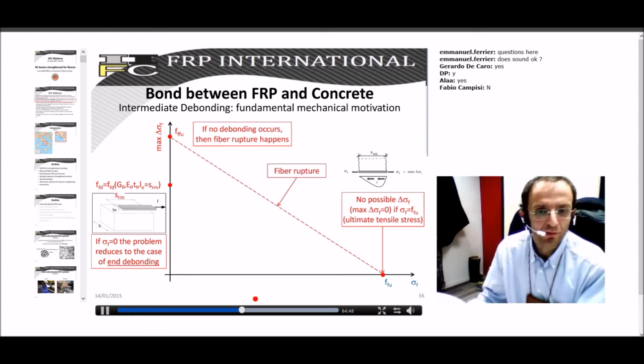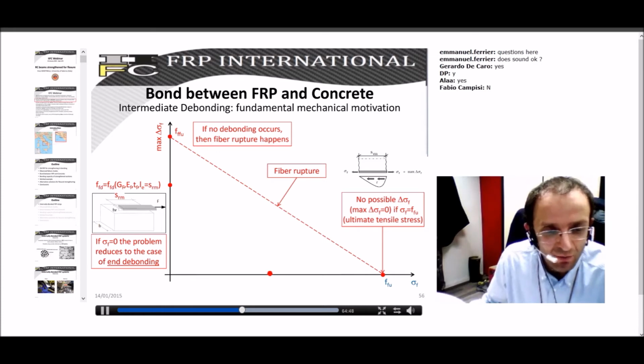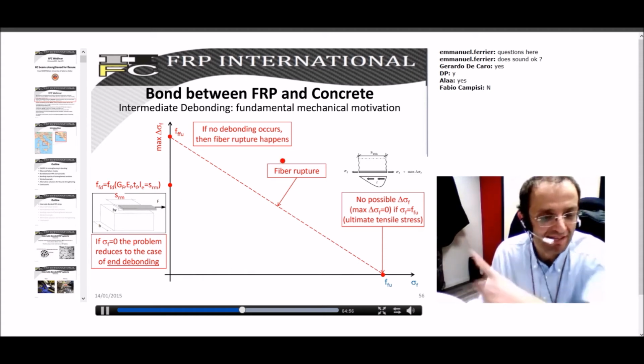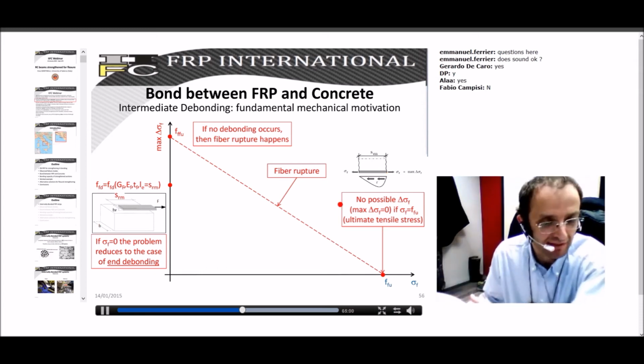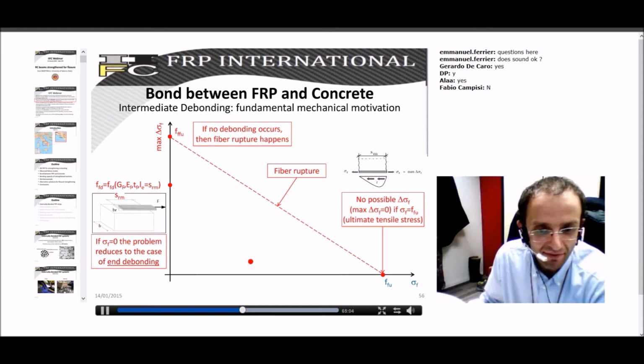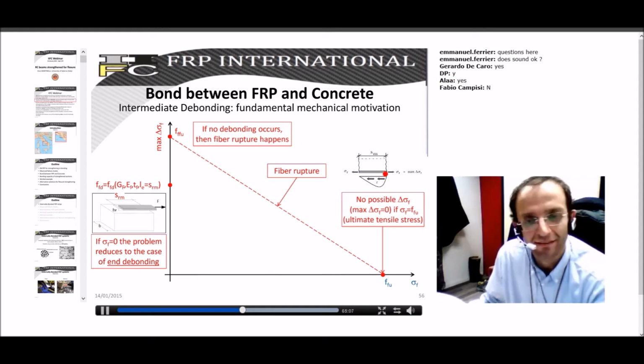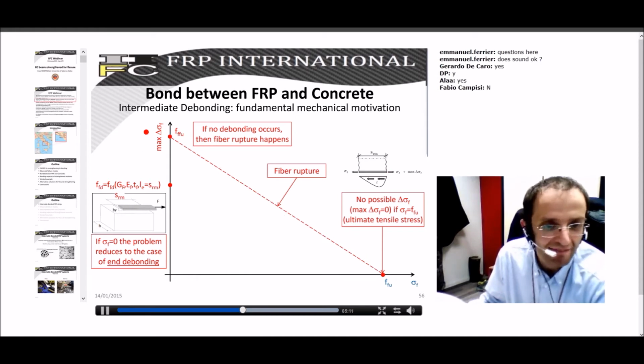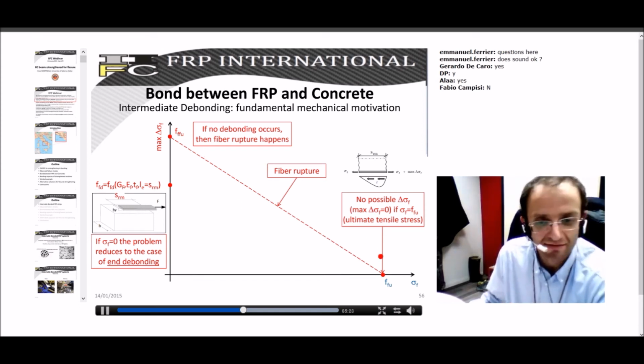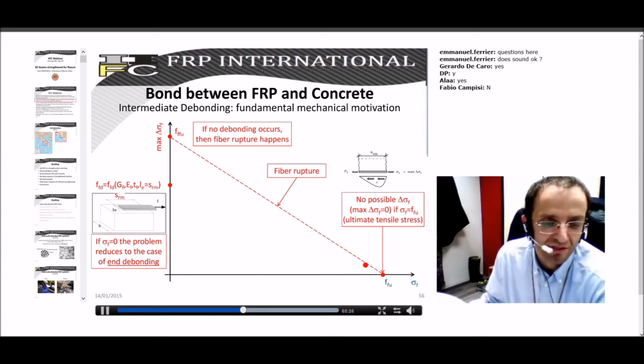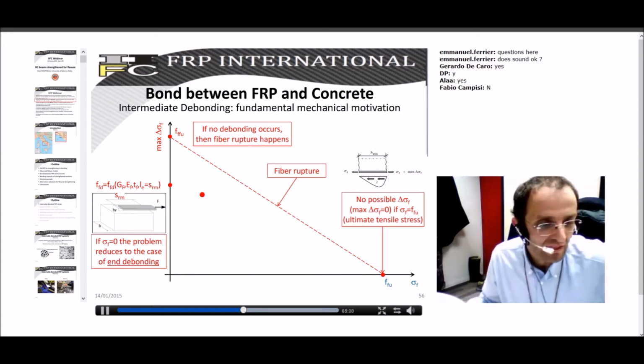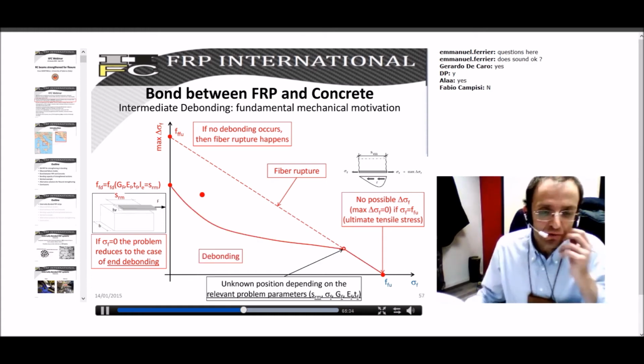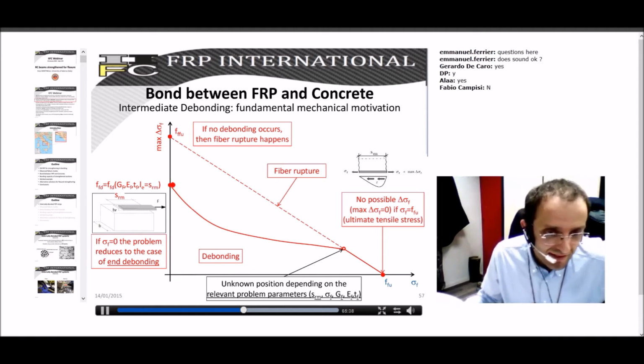Of course, it's easy to understand that for whichever sigma f, the one corresponding to this straight line is the increment in terms of sigma f resulting in having on the other side just FFU, ultimate. So if you have sigma f here, this is the increment you have on the other side to get FFU. So this straight line can never be overcome. The relationship between the applied maximum delta sigma and the initial one can never be higher than this, because this is the maximum strength of the system, which is represented by the axial rupture of the FRP strip.